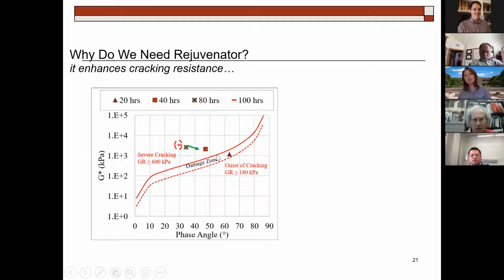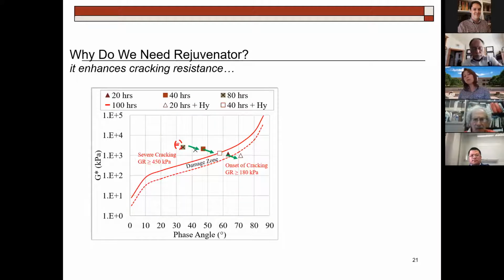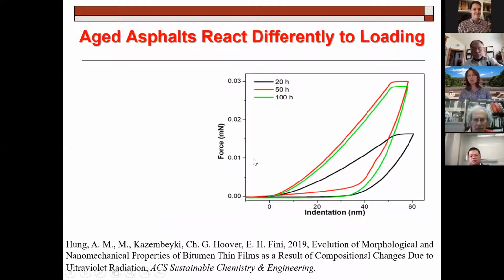So these are the aged ones. You can see the 100 hours is way past severe cracking. Let's see if I can reverse it with rejuvenator. I add the best rejuvenator we have found so far. You can see they shift a bit, but the one that was 100-hour aged didn't even move. It's right there. This one with the circle around it didn't move. Well, the 20-hour one, I could move it. See that triangle now is low, but the one that is severely aged, like the 80-hour one, there's no hope. The 100-hour one, no hope. So you have to watch what the critical aging point is to make sure that your asphalt doesn't die out.